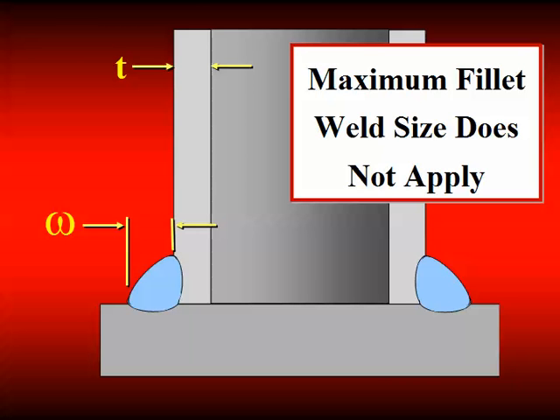Now here's another abuse. That maximum fillet weld size does not apply to this situation at all, does it? This is a T-joint, and you're never welding on an edge. There's no edge involved. For tubular members going down to base plates, it's routinely required for you to put in a fillet weld that's larger than the thickness of the tube in order to get a throat dimension required to resist the load. And I don't know how many times I've gotten a call from designers who say, my wall thickness on my tube is 3/8 and I need a fillet weld, and the fillet weld needs to be 3/8 leg size, and the code says it has to be 1/16 of an inch less. How do I handle that? It doesn't apply to this particular situation.